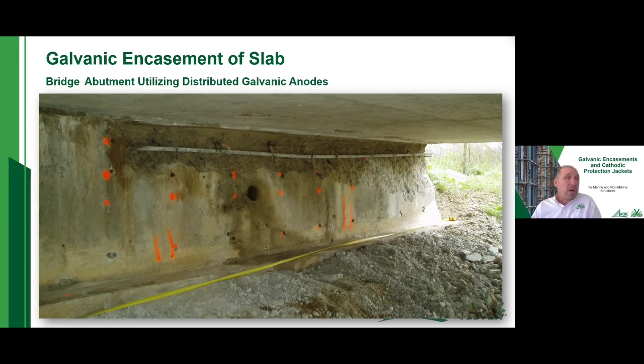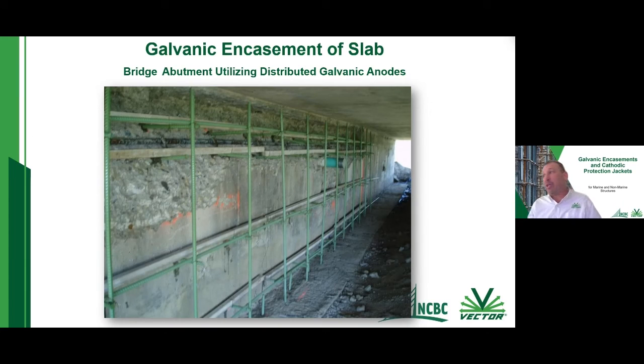So those were all the delaminated concrete was removed. They came in, added some new steel. In this case, they actually used epoxy coated steel. So they came in, added new reinforcing steel. You're going to want to make sure that this epoxy coated bar is continuous, or that it has a metallic path to your original steel.